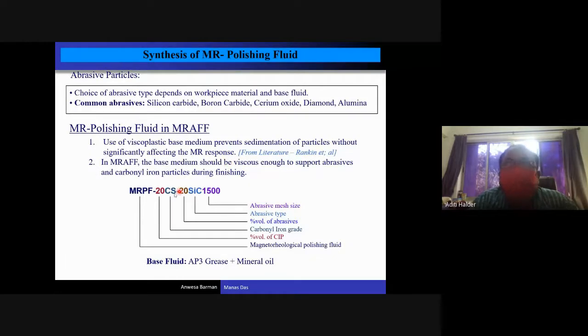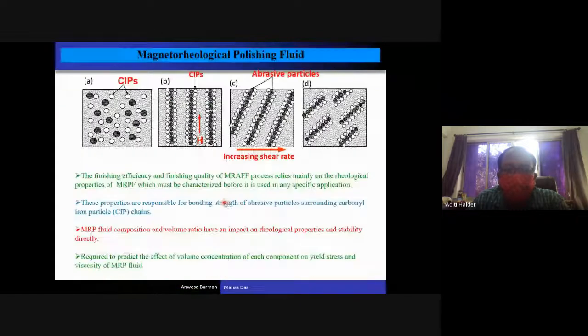So this normal MR fluid, this magnetorheological polishing fluid, is 20% by volume of CS grade CIP iron particles and 20% by volume silicon carbide abrasive particles of 1500 mesh size. This is the kind of nomenclature we have used. This one we shall discuss later.